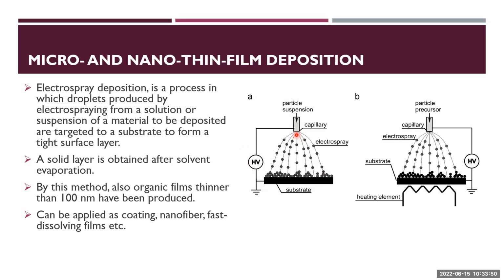Usually you dissolve your polymer in an organic solvent that evaporates quickly, for example, dichloromethane. Then after it sprays, it will make this kind of film, because the dichloromethane evaporates very fast and the flow rate is very small. Basically, it will evaporate just during the flow, or even if there is a little bit, it will evaporate here. And if you need assistance, sometimes you can apply heating to quickly evaporate the solvent.